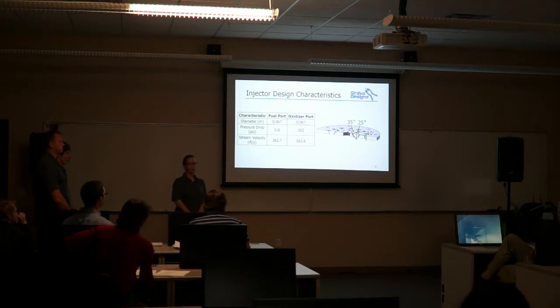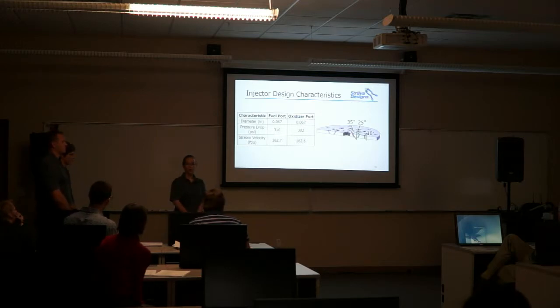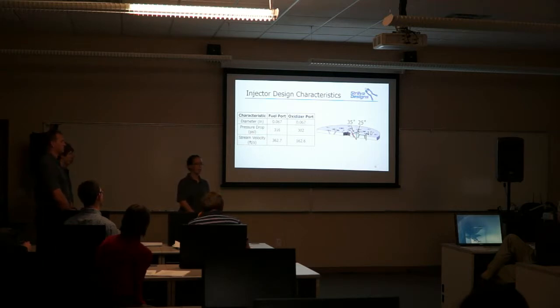We opted for a 60-degree overall impingement angle. We chose this because with a greater angle than 60 degrees, we run the risk of having backsplash of the propellant onto the injector plate, which can cause damage. With an angle less than 60 degrees, the length of the streams before impingement gets much longer, and we run the risk of having the streams go unstable before reaching impingement, which means that we would not have the spray pattern that we expect. Within that 60 degrees, we selected the individual impingement angles to balance the momentum of the